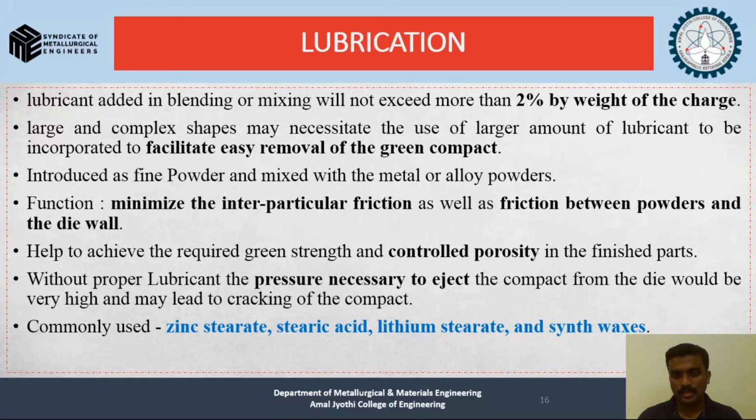The lubrication process will also ensure that there is a controlled porosity in the finished product. So what is the reason if we are not using proper lubrication in our process? Without lubrication, the pressure necessary to eject the compact from the die would be very high, which will lead to cracking of the compact. And commonly used lubricants are zinc stearate, stearic acid, and lithium stearate, and synthetic waxes can also be used as common lubricants.